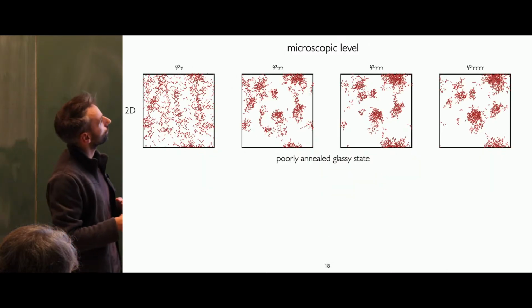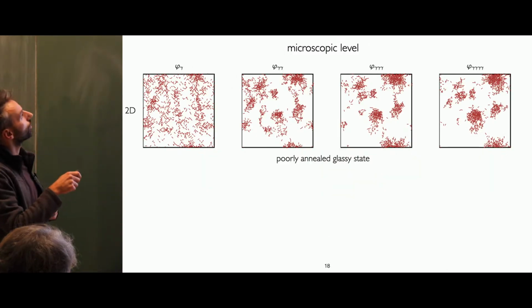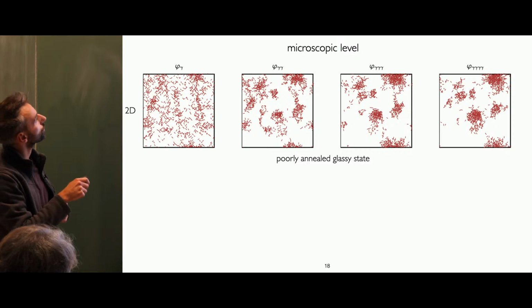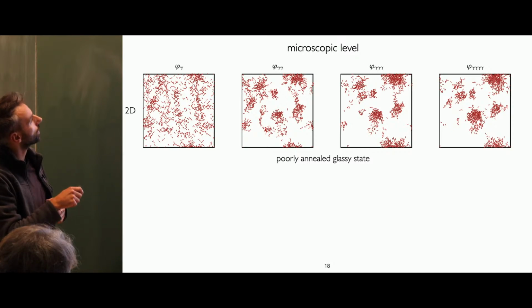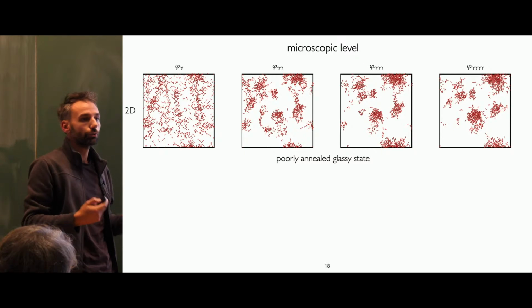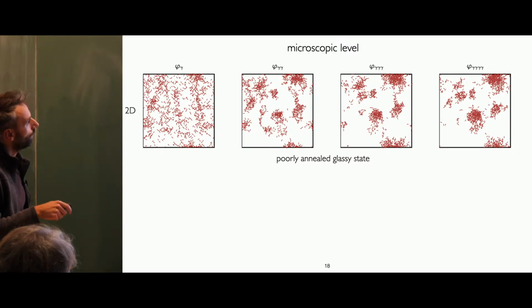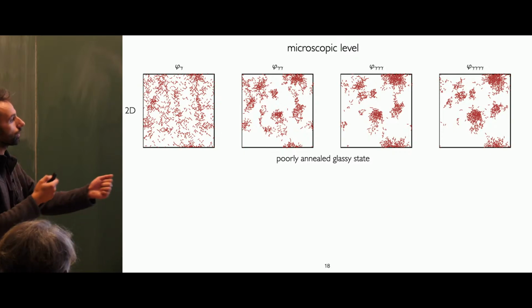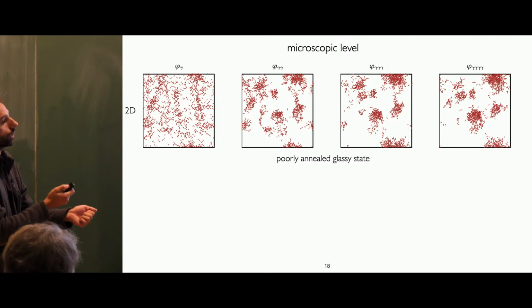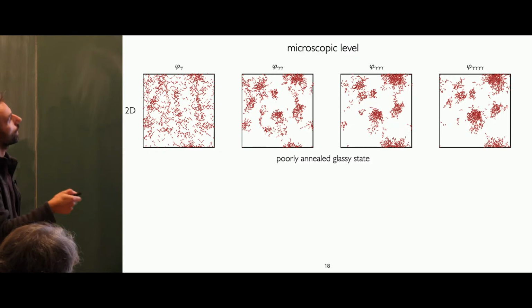And so now at the level of the microscopic, I don't only have the global coefficient, but I really have the coefficient for all the pairs. So I can ask, is there anomalous variation of energy in my system? And indeed, what you see is that the change of energy is not homogeneous, but you will have some regions that will show a large variation of energy, which will help you to predict where there are going to be large deformation.